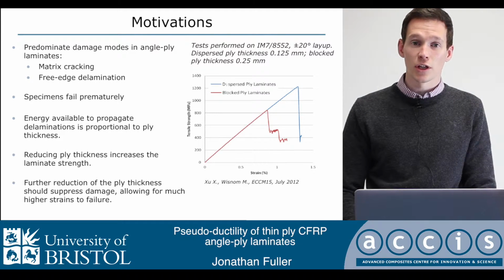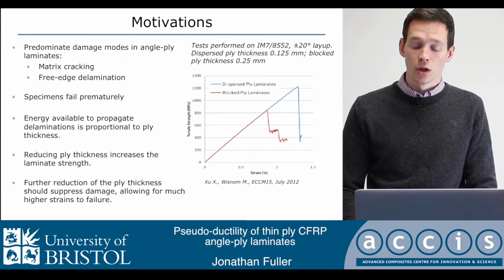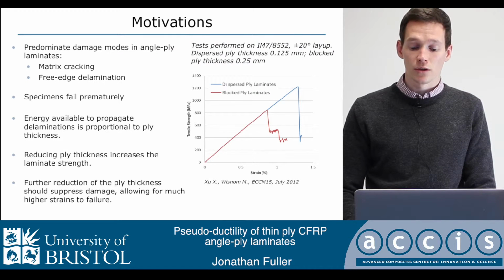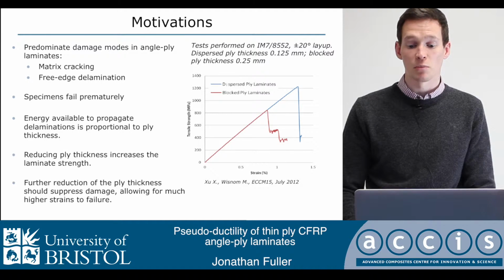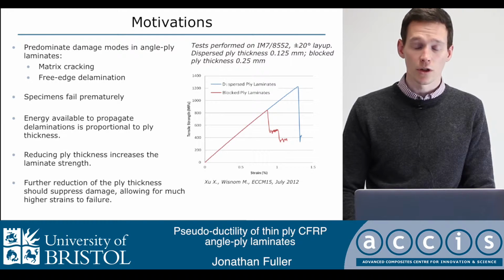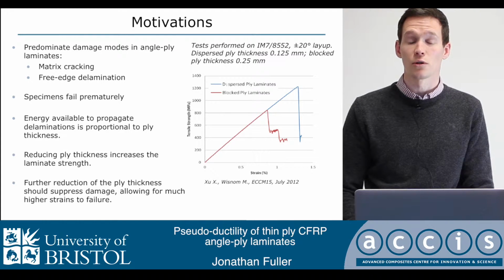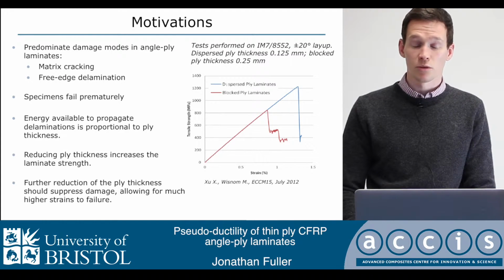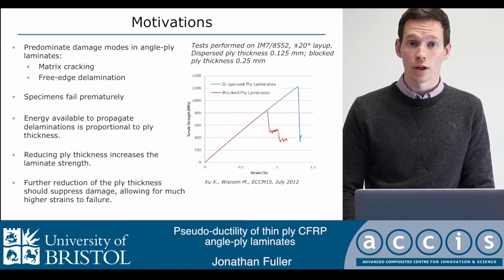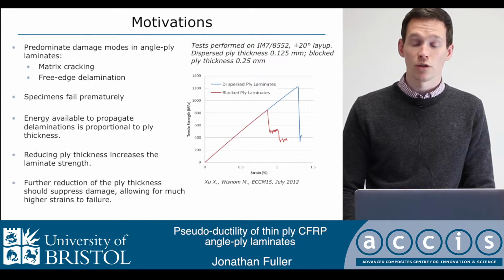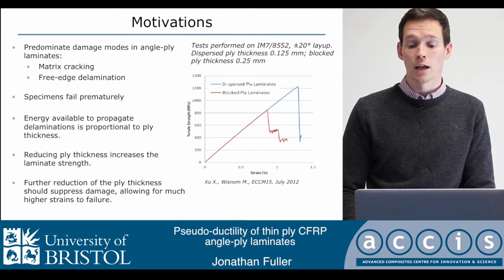Now, energy calculations show that if you reduce the ply thickness, you can increase the strain to failure and the laminate strength, which is shown for the dispersed plies by the blue line. So the idea is if we further reduce the ply thickness using a spread tow fabric or UD tape, we can actually completely remove these damage modes and create a non-linear stress strain curve.